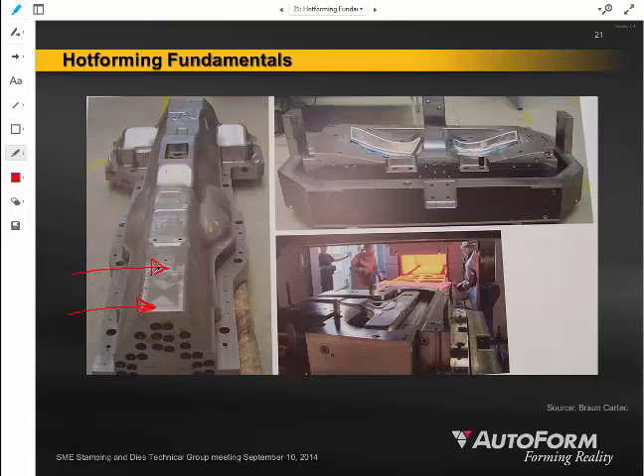So you get these very abrasive tools with this aluminum-silicon coating on it. You're taking it up to a high temperature and forming it against this punch, and we're seeing high wear conditions. And of course, it's a wear condition that you can't necessarily control very effectively with lube, at least not the lubes we're used to using, because they don't behave the same. The lube would have to perform from the top end of the temperature range to the bottom end. Most lubes that we might work with have optimal temperature ranges that are only maybe 50 degrees Celsius wide. It'll be good between 50 and 100 degrees Celsius. But you're not going to find a lube that performs well from 400 degrees Celsius all the way up to 800, 900 degrees Celsius.